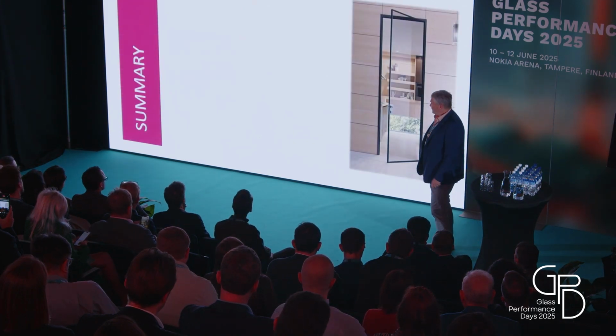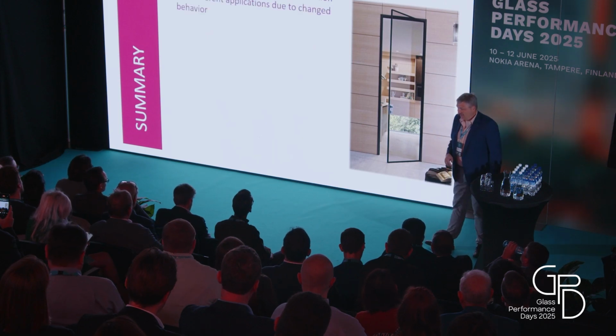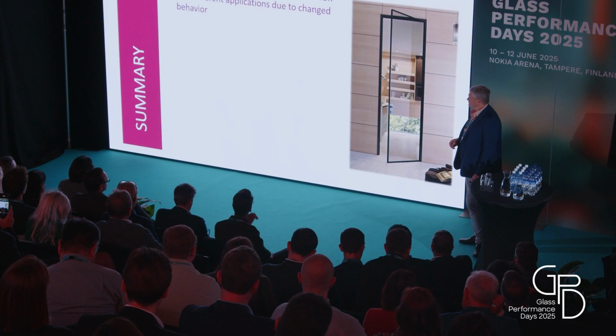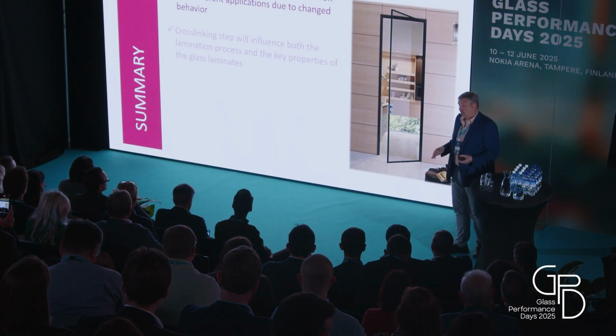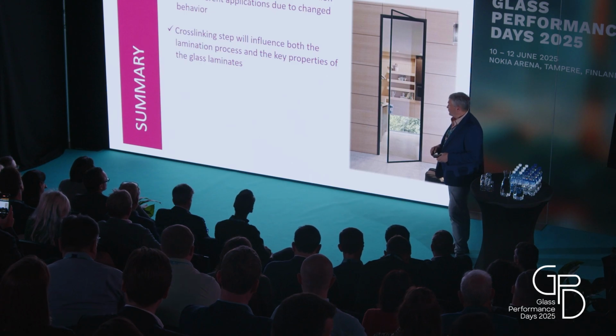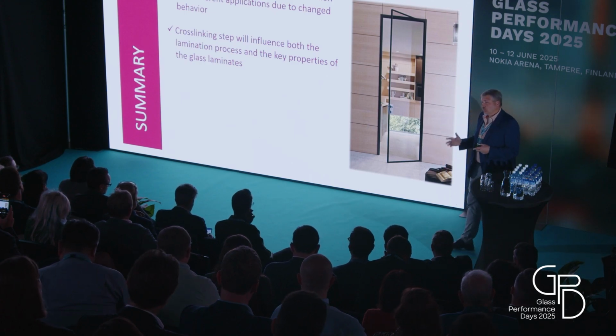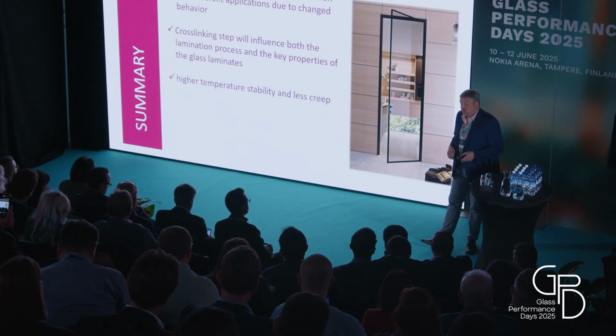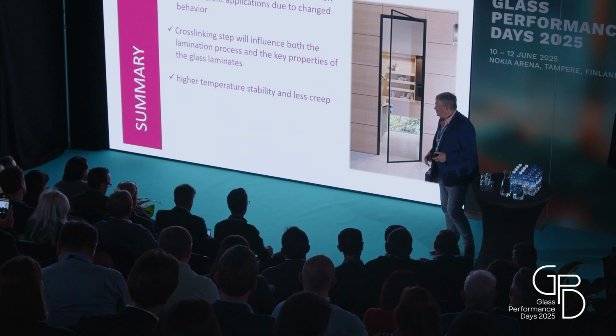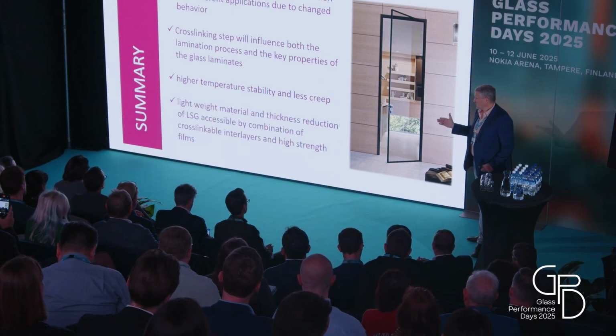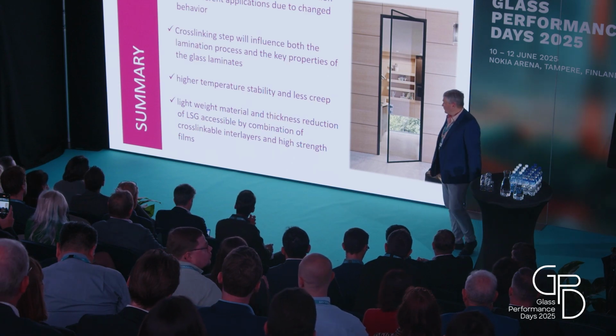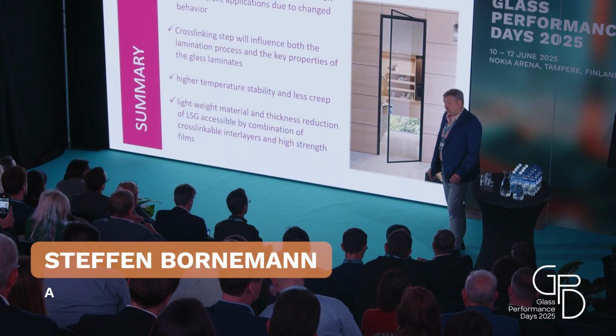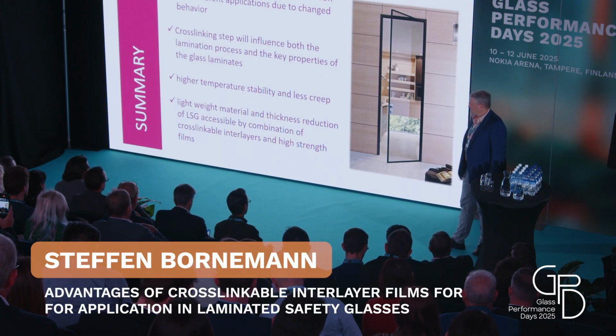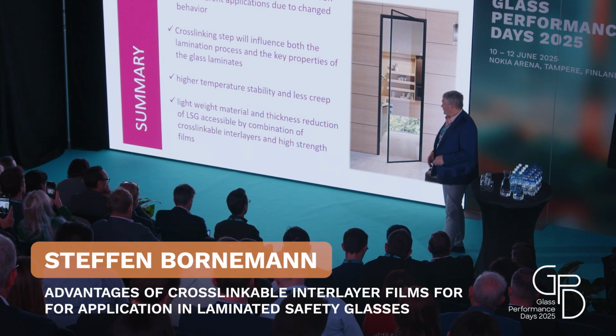Ladies and gentlemen, at the end of my talk, I would like to summarize a little bit before you can enter this door. We were talking about cross-linkable interlayers in glass lamination. They can offer different applications because they have slightly different behavior than the normal films, as you know. I have shown that the cross-linking step will change the material properties and the key properties of the laminated glass. As an example, I have shown you higher temperature stability for cross-linked materials, less creep. This means more load-resistant glass. And I have shown some results from thin or lightweight materials for thickness reduction by combination of cross-linkable interlayers and high-strength films.